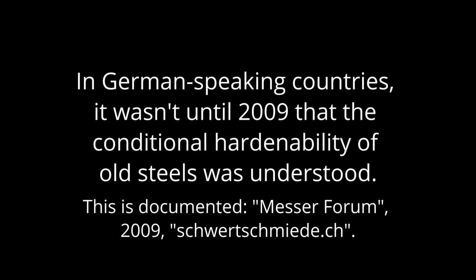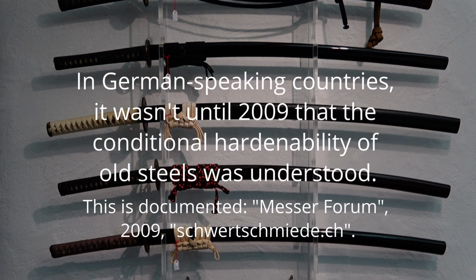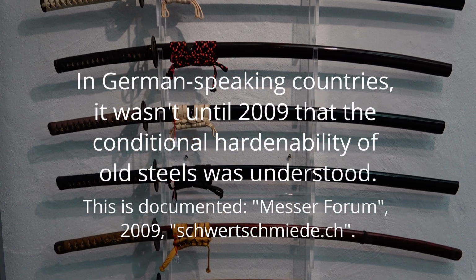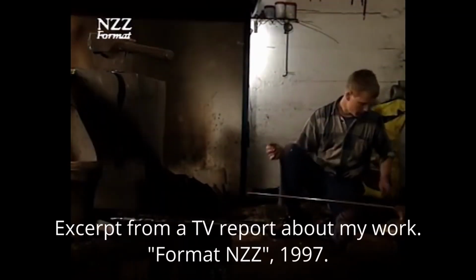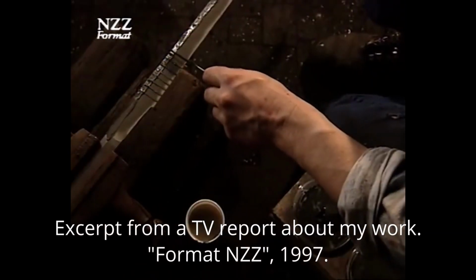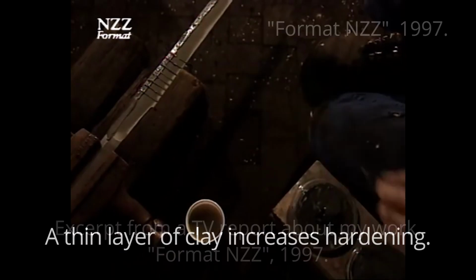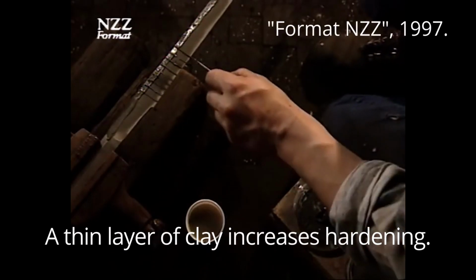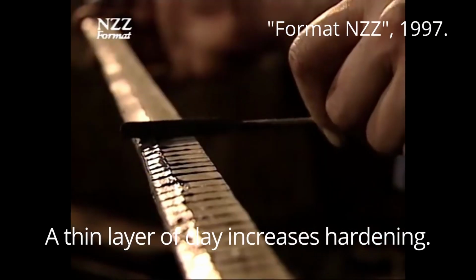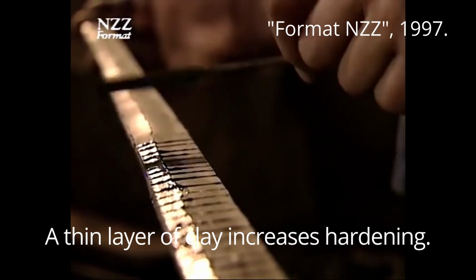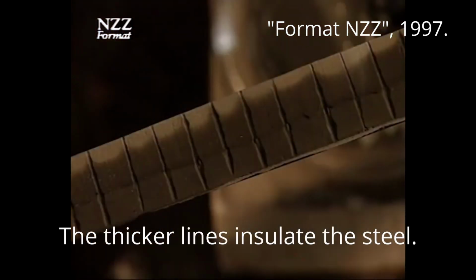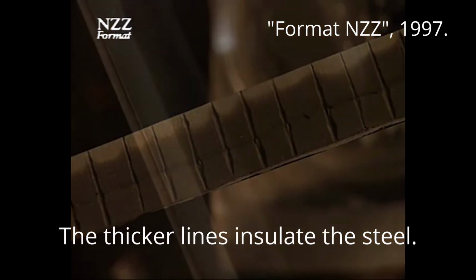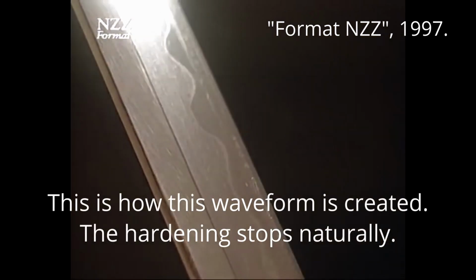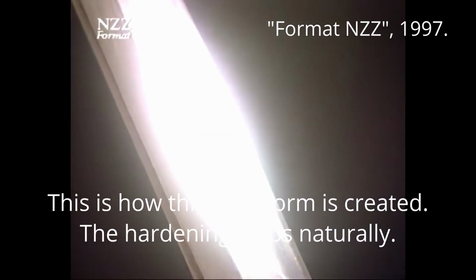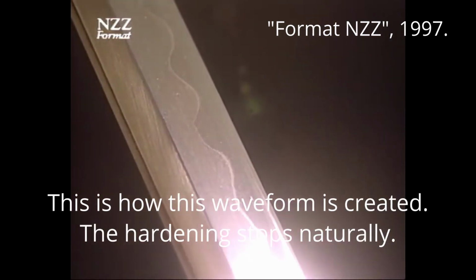The most famous example is the Japanese sword. It is often assumed that Japanese swordsmiths deliberately create only a narrow hardening along the cutting edge. The truth is that the steel does not allow any further hardening. This narrow hardening along the cutting edge is found in all non-fused steels. Worldwide, anyone who produces their steel correctly from iron or in the reduction furnace, used in the earlier days, and hardens such a blade later, only obtains a narrow hardening along the cutting edge.